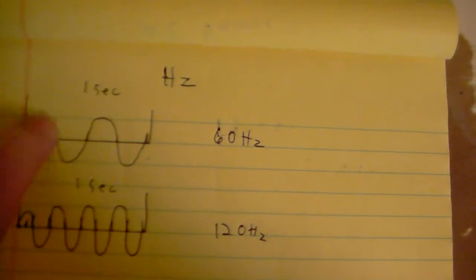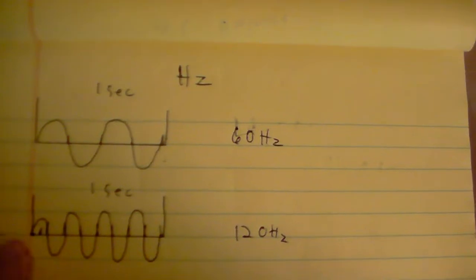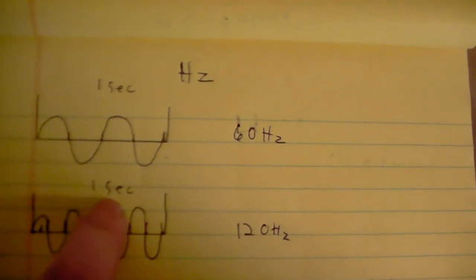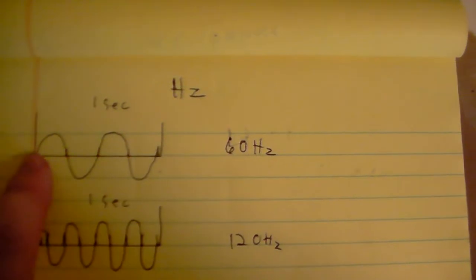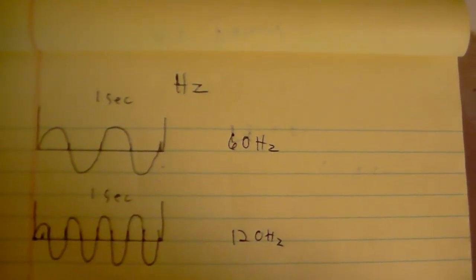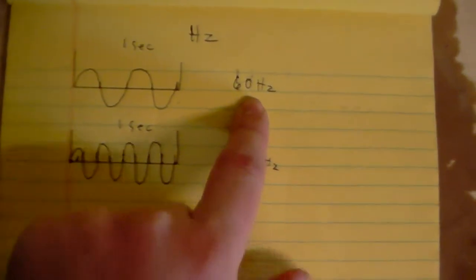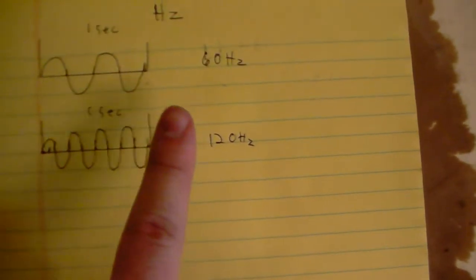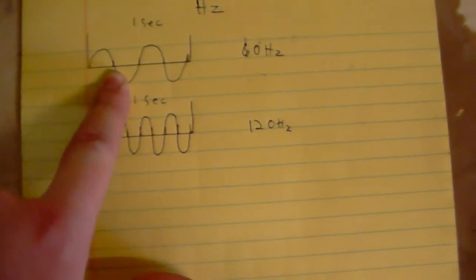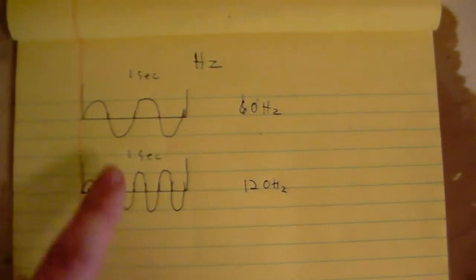So this is what hertz control is: how many times you do those switchbacks in 1 second. So 60 hertz won't have as many switchbacks as 120 hertz. Now, the reason that this is kind of nice, the less switchbacks you have, the wider and hotter your puddle will be. So this tends to dump quite a bit more heat into the plate, especially when you balance it out. Okay, so the wider your bead will be, the hotter it will be.